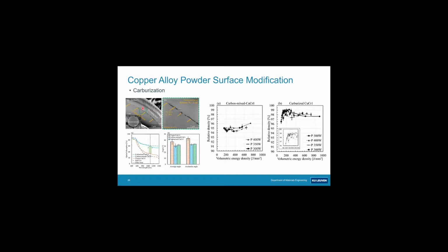So this is a FIB cross-section of such a particle. This is the coating layer, but here you see that there is a reaction layer. And if you would look in more detail along the grain boundaries of this copper particle, you would find a lot of chromium segregation. So first, there is a chromium carbide layer, a small chromium depleted zone, and then a lot of chromium enrichment because of chromium diffusion along the grain boundaries.